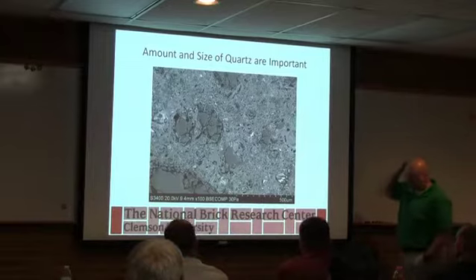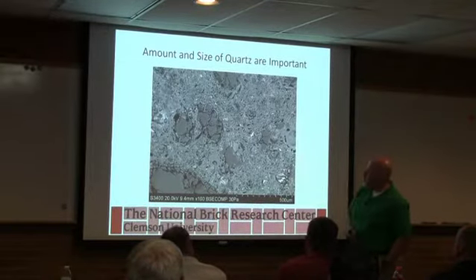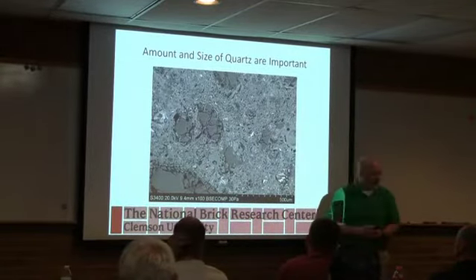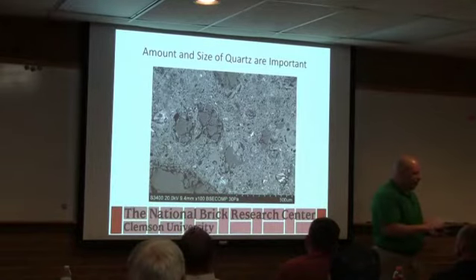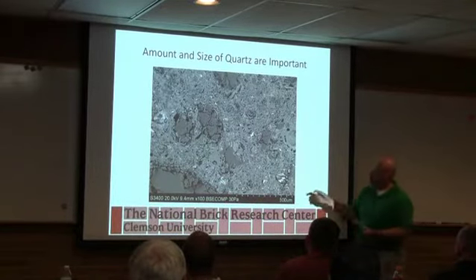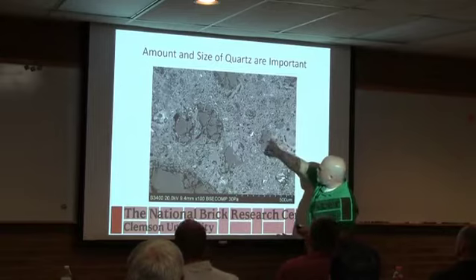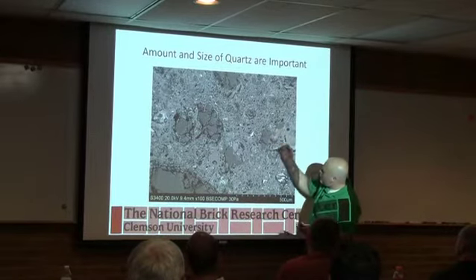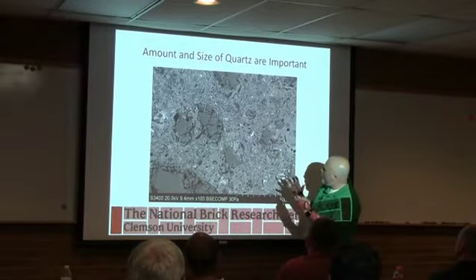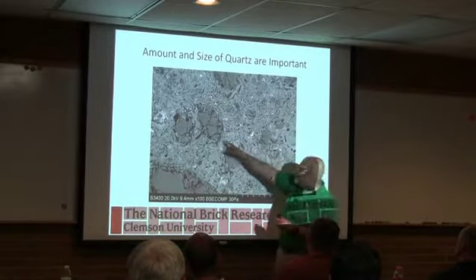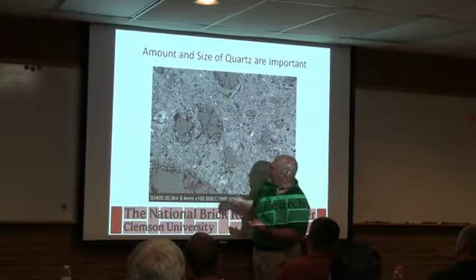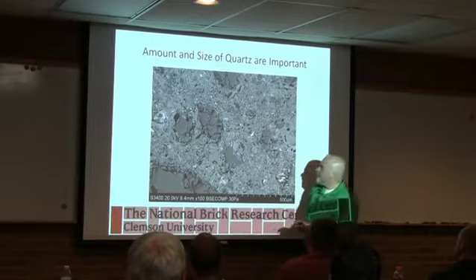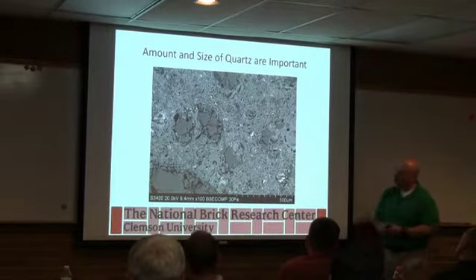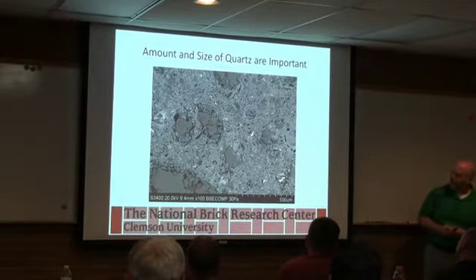So this is what you would see if you could look at your brick under a microscope. This has been polished, so everything's nice and flat, and it's easy to see. It's real easy to pick out the quartz grains. There's always sort of a halo around it where it's tried to pull away, and they're usually all cracked to hell, just like in here. Okay, so that is the way you look for quartz grains.